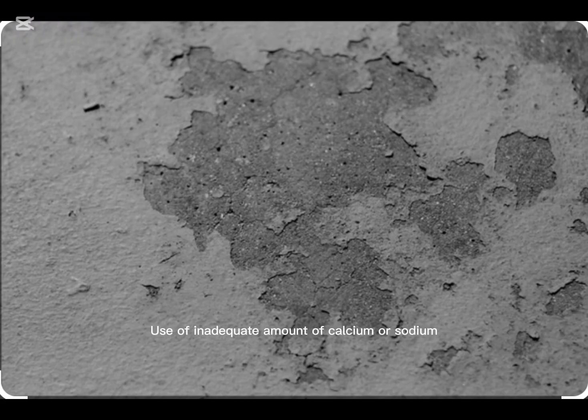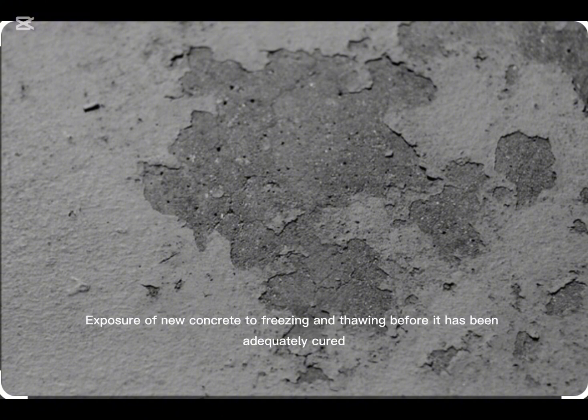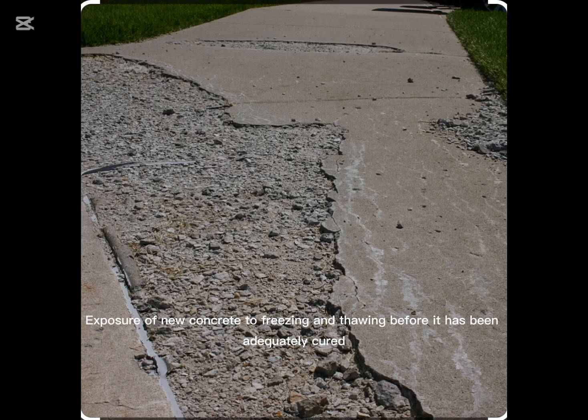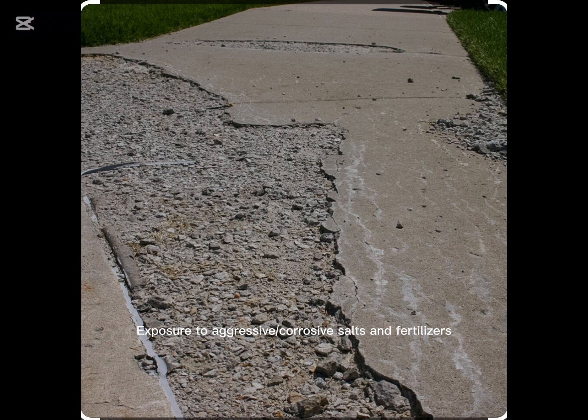Causes of concrete scaling: the use of non-air-entrained or less entrained air agents in concrete mix, use of inadequate amount of calcium or sodium chloride deicing salt with lower strength concrete, using concrete with low strength or high water cementitious ratio, finishing work executed with bleed water at the top of the surface, improper finishing of concrete slab, early or accelerated drying of the exposed concrete surface, lack of adequate curing and protection, exposure of new concrete to freezing and thawing before it has been adequately cured, exposure to aggressive corrosive salts and fertilizers, inadequate use of supplementary cementitious materials, choosing improper curing methods.